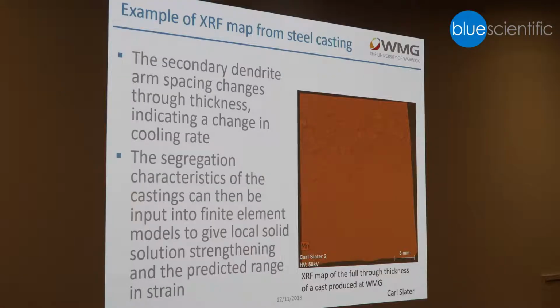And this slide just shows a typical example of something that we cast and then later analysed to see the segregation behaviour. And as you can see, there's a secondary dendrite arm spacing change through the thickness, indicating a change in cooling rate. And this data was obtained from Carl, who then uses this segregation characteristic to input into finite element models, and that gives local solid solution strengthening information, and it can predict